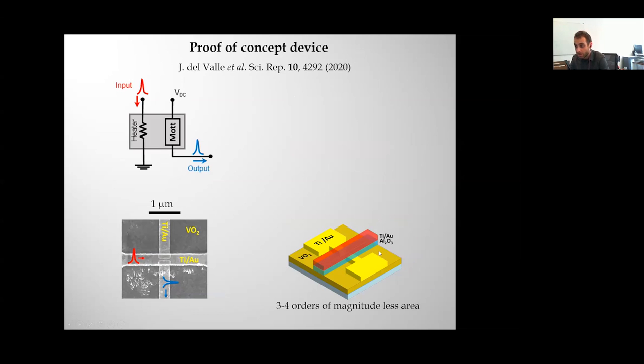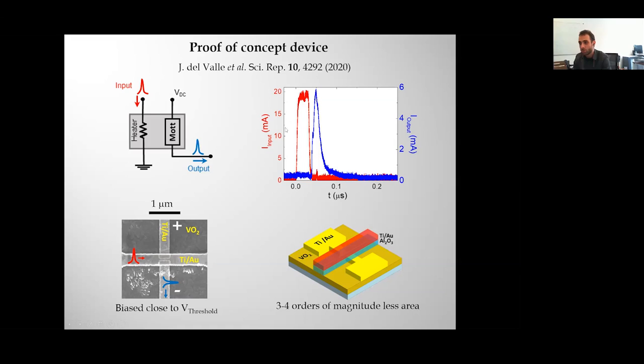In between, there is this aluminum oxide barrier, which would be an electrical insulator, but it's a good thermal conductor. The idea is that we are going to bias this gap very close to the firing point, very close to the threshold voltage, but below it, so that any current spike that we send through this heater is going to be enough to push the system past the firing point and make it fire, make it go into the metallic state.